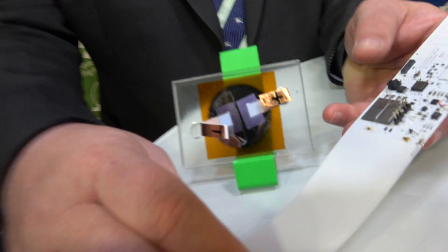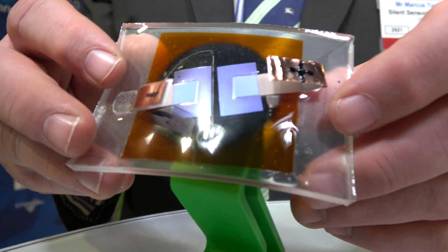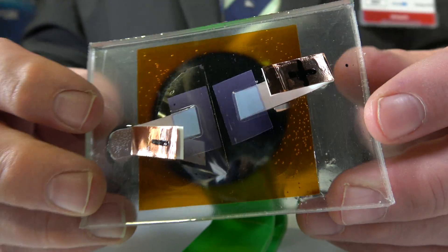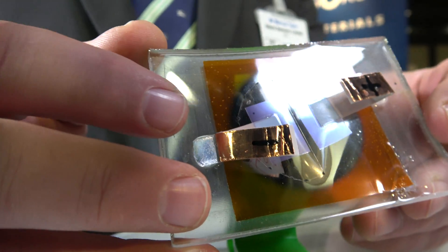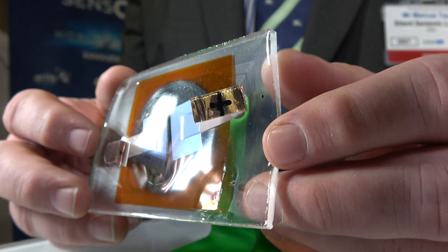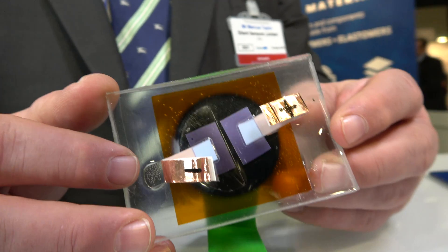But the main driver is safety. So tyres, first and foremost, are safety products. And this supercapacitor is a big deal? It's a big deal, because supercapacitors and capacitors in general don't like high temperatures. Typically, supercapacitors will stop to work at about 80 degrees. What's amazing about this material is it keeps working with almost no change in efficiency up to around 200 degrees Celsius, maybe more.